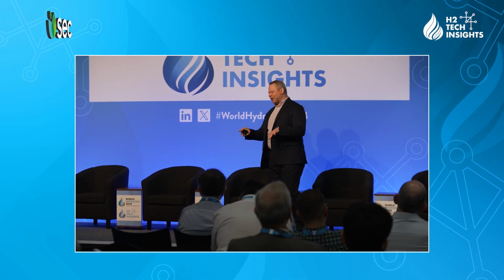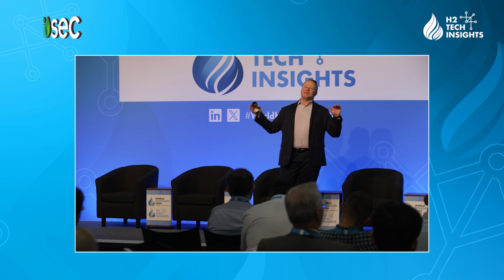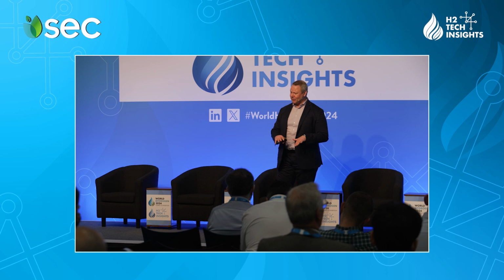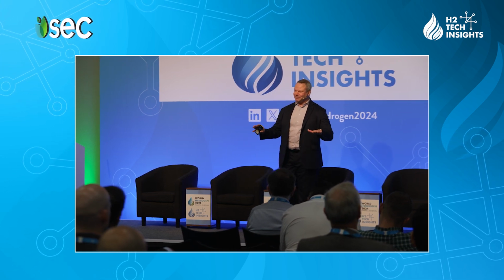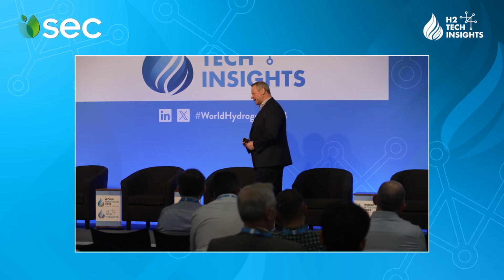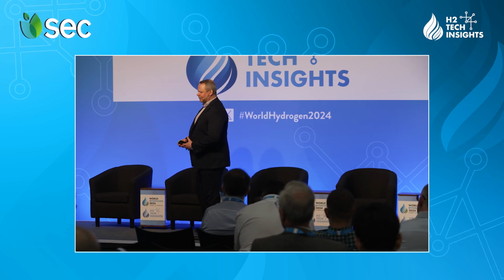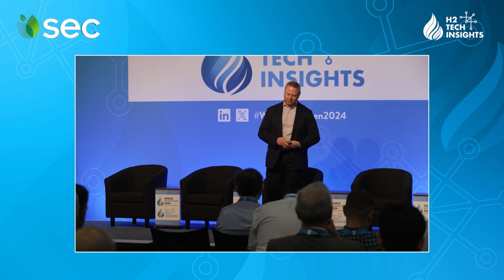So resistance and performance are correlated at this mid-range, again, simply because of a geometric effect of the PTL in contact with the anode. We want as much of that contact as possible. Water transport and oxygen transport are secondary. Water is 55 molar. Trust me, you will get enough. Okay? So this is a new finding, and we're talking with the national labs in the United States. With our new DOE grant, we're joining the H2NEW consortium and starting to work on problems like this. But I think that the academic and national laboratory teams should take problems like this up and try to understand this at a fundamental level.